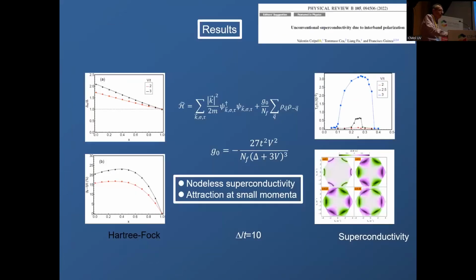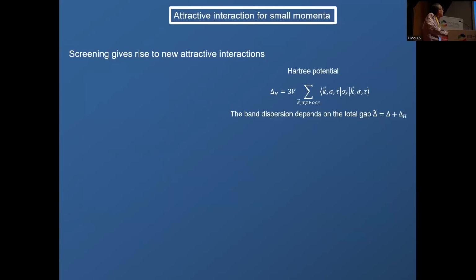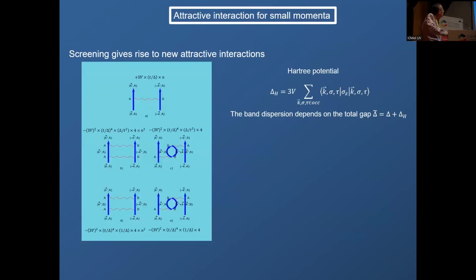But the thing is that at the end of the day, you have superconductivity, and we studied in detail which kind of superconductivity. A system like graphene has the Fermi surface split into two valleys, and it's a superconductivity which is not trivial in the sense that the gap is not constant, changes sign, has opposite signs in the two valleys, but within each valley it is finite. So it's a new kind of superconductivity, which we believe is probably related to the superconductivity found in twisted bilayer graphene. This is more arguments in favor of why you have attraction and what's the relation to the symmetry.